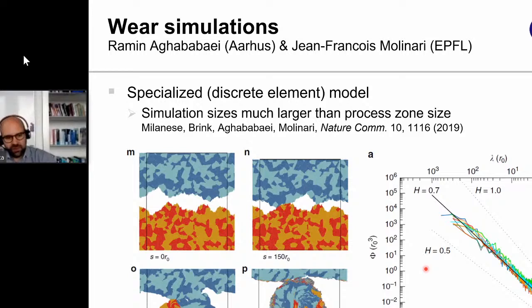But what they did, and what is very clever, is they designed their model in a way that the process zone is small, so that they can do simulation sizes much larger than the process zone size. And this is one of their calculations from Nature Communications that was published last year, in which they set up a rough surface. They slide on top of each other, and they see the formation of these wear particles. But what they did in this paper is they analyzed the surface roughness after their sliding calculation has finished. So they slid for a very long distance. And the right-hand side here again shows the power spectral density of their surfaces. The power spectrum is a function of q, and they also find self-affine scaling with H between 0.5 and 1, on the order of 0.7.